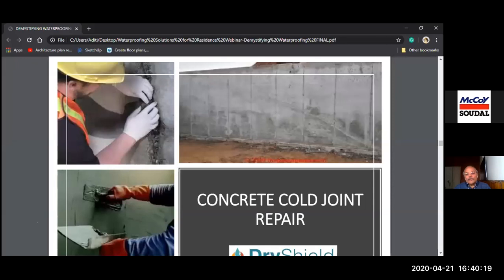Now these cold joints have to be repaired properly before doing anything else. So even if you have to do some kind of injection grouting in that wall, these cracks have to be repaired first. If any coating has to be done, even then these have to be repaired first. Now, how do you repair them? You have to first open them up, clean them properly with water, and use a good ready mix mortar.